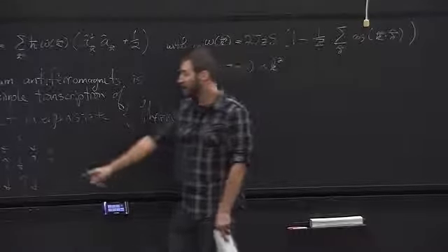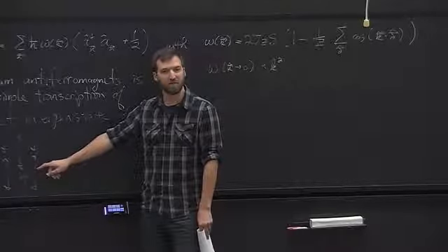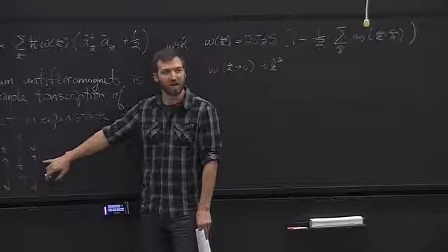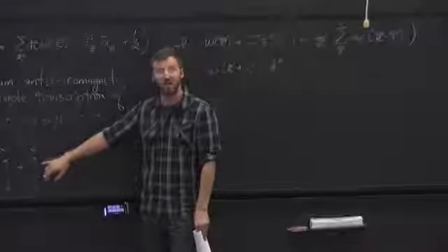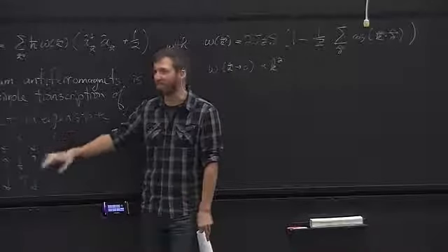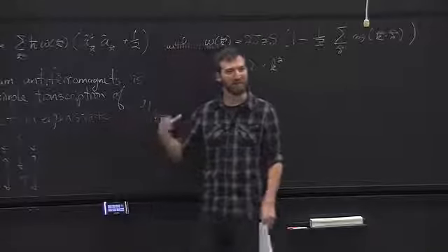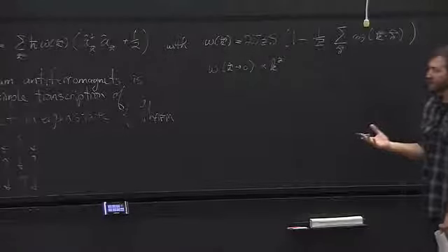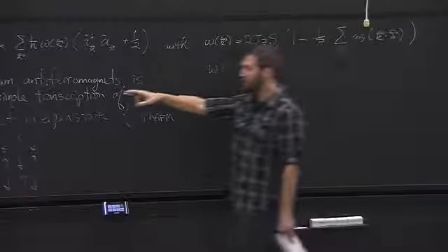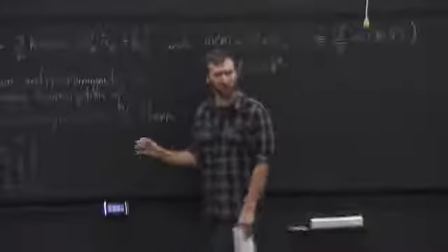So in the end, what you find in an antiferromagnet is you still have a symmetry breaking. You still have a staggered magnetization for the order parameter, but its magnitude is significantly reduced from its maximum classical value. So if these are spin 1/2 spins, the staggered magnetization should be a half maximum, the expectation value of the staggered Sz operator. Whereas in the spin 1/2 quantum Hamiltonian, it's actually reduced to something like 0.3. So there's a significant reduction of the magnetization in that case.